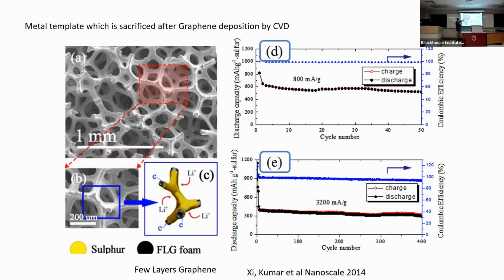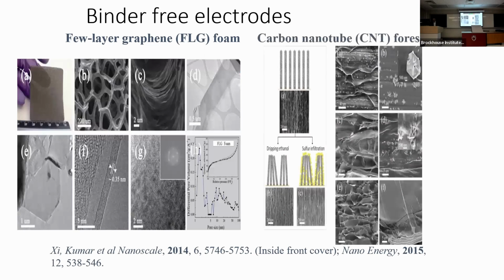At this magnification, you can't see. Most of those micropores or mesopores are within the structure. Maybe the next graph will show you that. Yeah, you can see that. This is the few layer graphene. There's a large amount of capacity available at all those surfaces. And although this is at the lower magnification, this is the higher magnification. And similarly for the carbon nanostructure, we can look at very high magnifications as to where those capacity resides, where the sulfur interacts with the structure and actually produces the capacity.